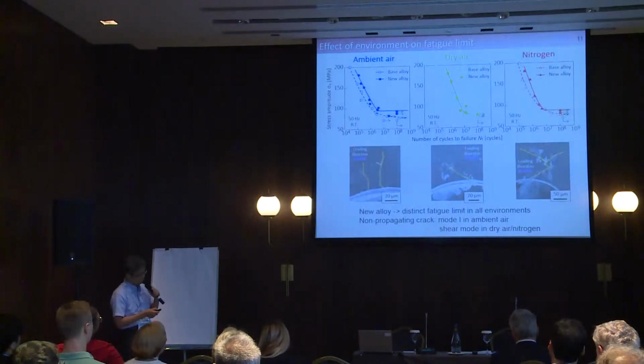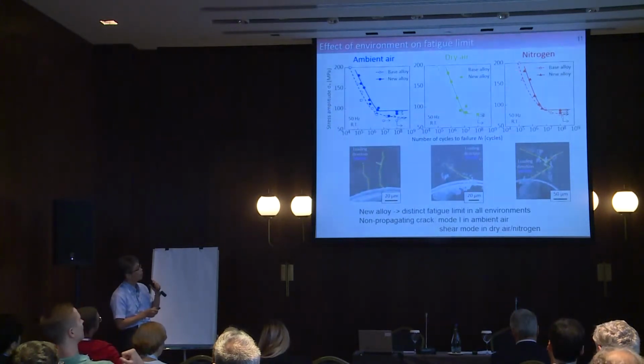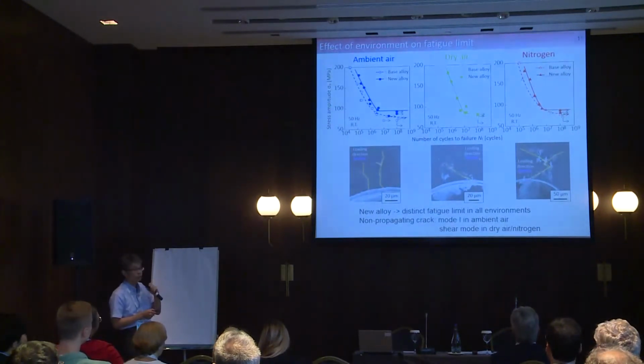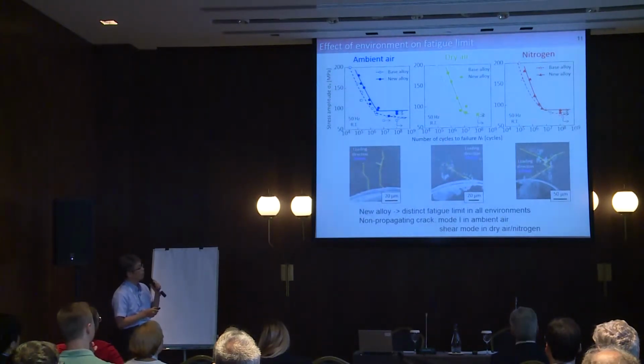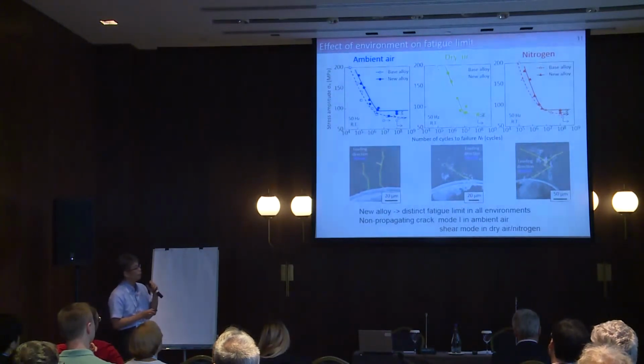So far, I've checked the new alloy property only in the ambient air, but here I show you the results checked in dried air and nitrogen. The new alloy clearly shows a distinct fatigue limit, even in the dried air or nitrogen, irrespective of the environment. And they are also found to be the limits of small crack growth. And the crack mode is mode 1 type in the ambient air, but shear mode in dried air and nitrogen.